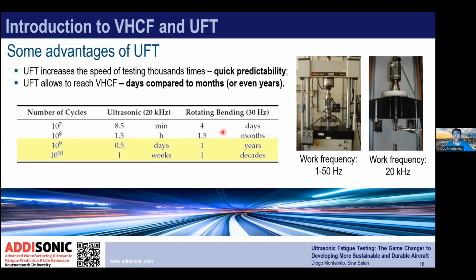But it still is a great improvement compared to a conventional test method. And if we wanted to reach 10 to the power of 10 cycles, it would take us 1 week on ultrasonic, while at 30 hertz, working 24/7 non-stop, that would be 10 years, basically, because it's tenfold the number of cycles. So this opens an opportunity to get data for the very high cycle fatigue regime. Or if you want to look at it another way, if I'm not interested in 10 to the power of 9, I'm interested in 10 to the power of 8 cycles, well, we can do that in just a couple of hours compared to months in rotating bending at 30 hertz. So you can get data very quickly in our testing.